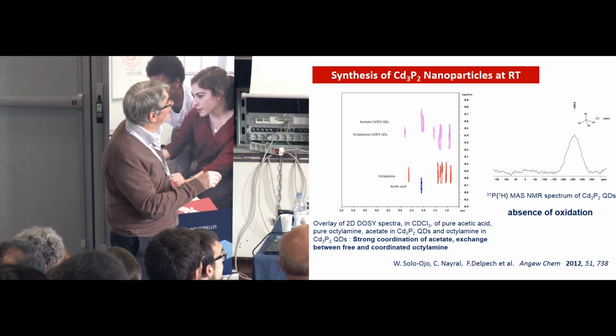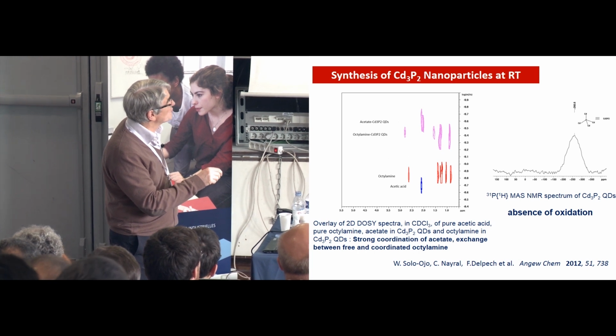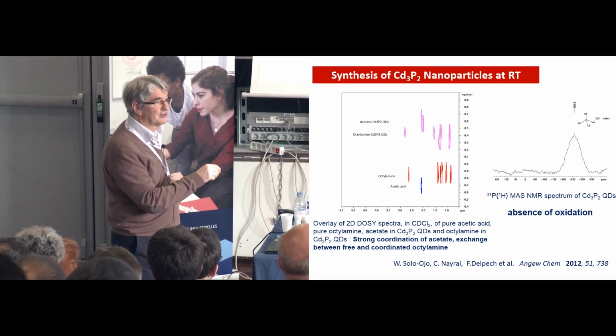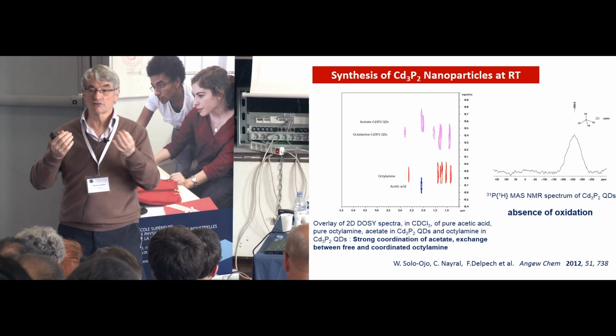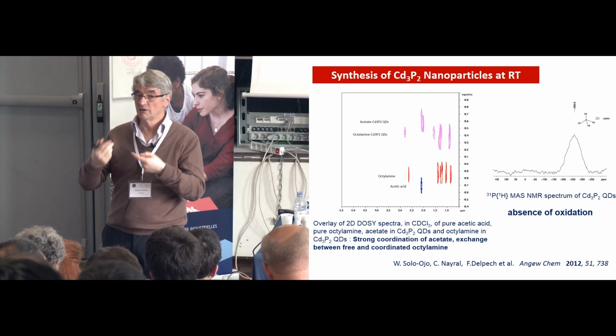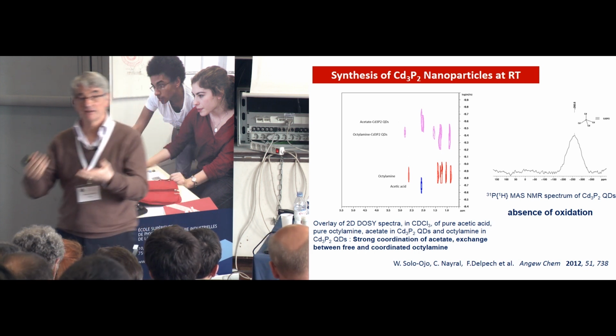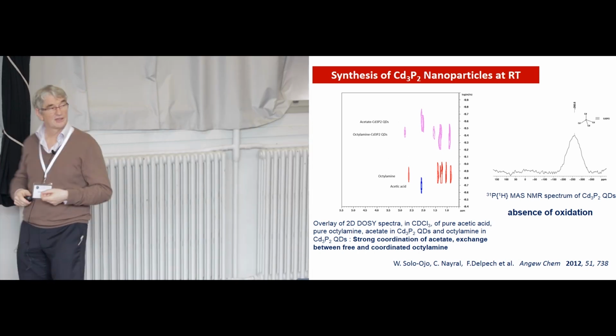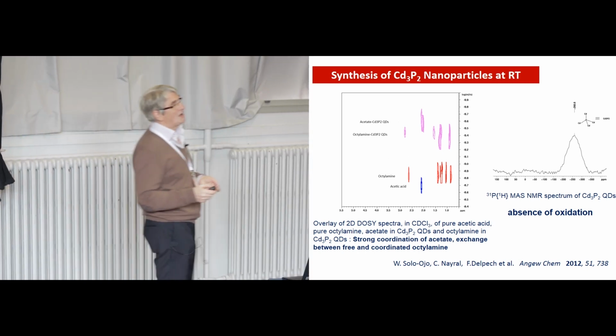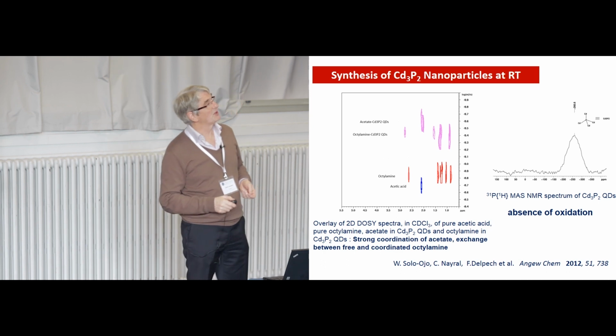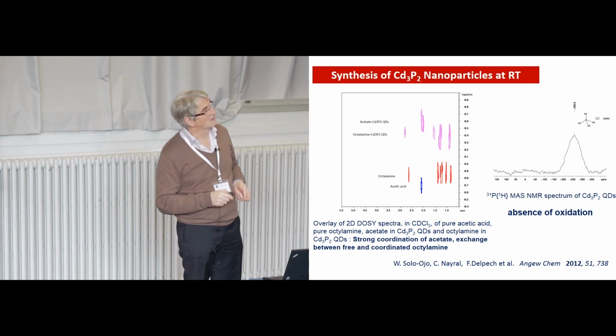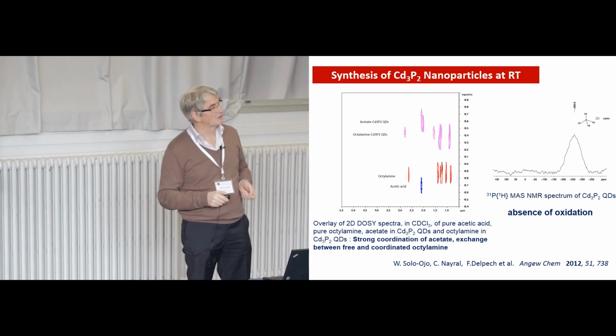And no oxidation. You know, if you remember well, there was a peak in this region. But if you work at room temperature, there is no degradation of the ligand, and so no water formation and no phosphate formation.